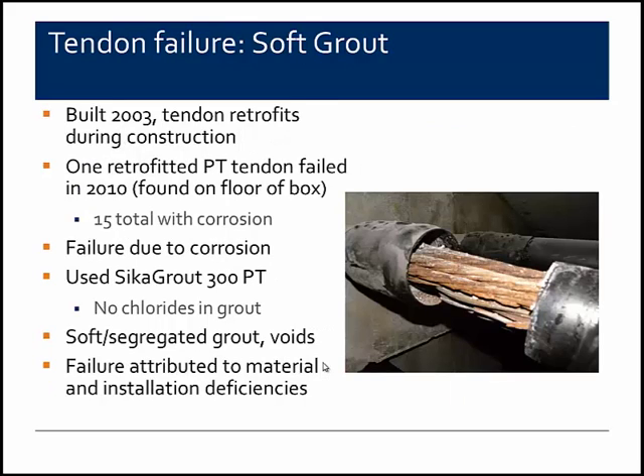And there have been some tendon failures attributed solely to the soft grout. There was a significant bridge in the Florida area built in 2003, and they actually had to do some tendon retrofits during construction, and it was those retrofitted external post-tension tendons that failed. And the slide on the right shows you one of those post-tension tendons and the failure that occurred. They actually found one that had completely failed, and a subsequent investigation found 15 others with corrosion.